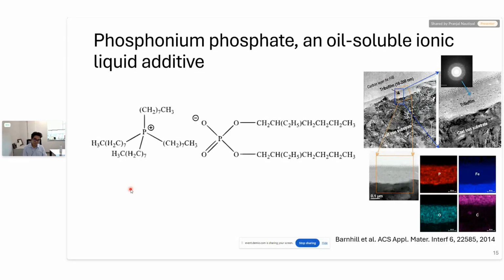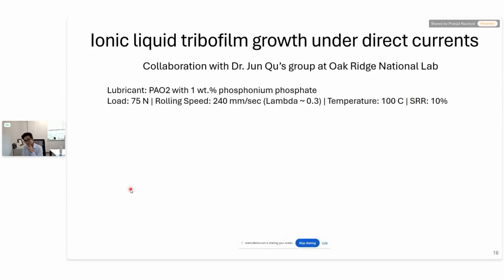Most of these prior studies are done under unelectrified conditions, so traditional mechanochemical conditions. So in this study, we investigated the formation of tribofilms by this ionic liquid in the presence of electric field using MTM. We obtained these samples from Dr. Jun Qu's group at Oak Ridge National Lab. We added 1% phosphonium phosphate in PAO2 oil, and then we conducted the tests under the conditions I have listed here.